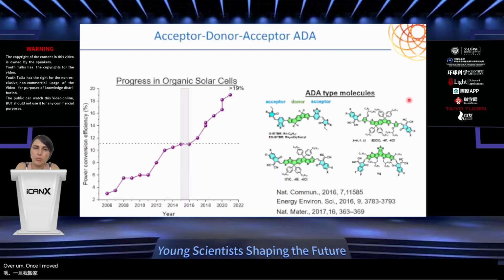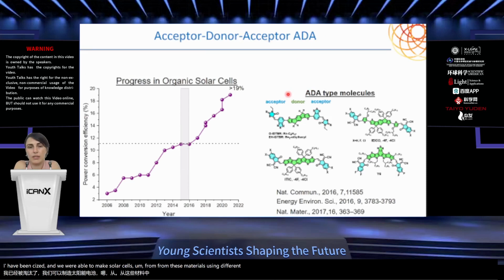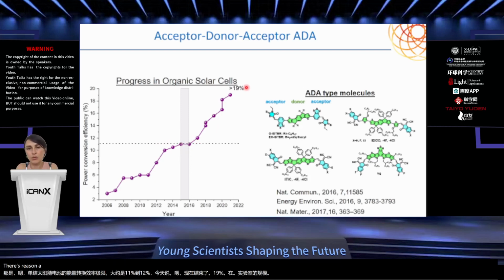However, once I moved on to my postdoc, something magical happened at the time in the field of organic photovoltaics, and I've been fortunate enough to be in there. The electron acceptor-donor-acceptor type, or ADA type molecules, have been synthesized, and we were able to make solar cells from these materials using different donor materials as well. From that moment onwards, the power conversion efficiency limit for a single junction solar cell, which was about 11 to 12%, is today over 19% at lab scale. There's obviously a long way to go forward. However, this has not been an incremental achievement in such a short time.